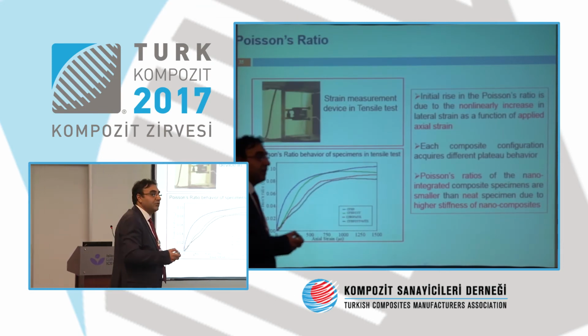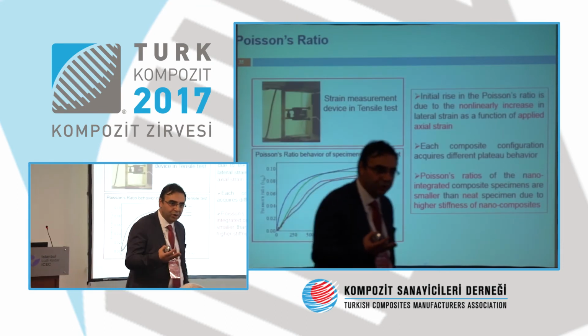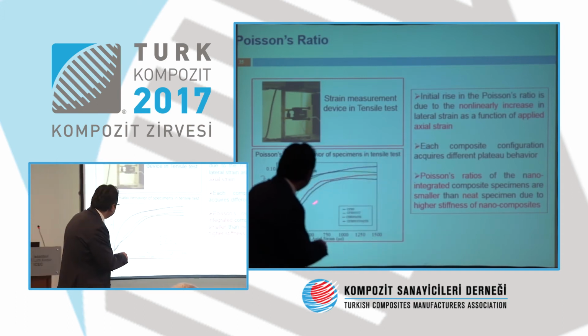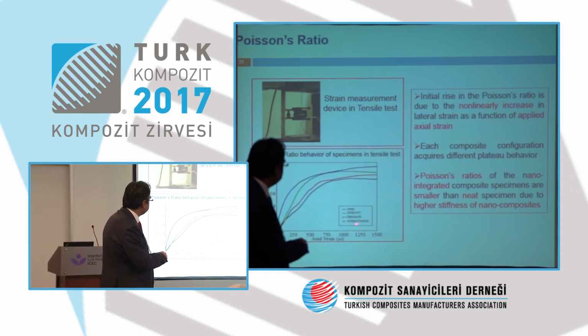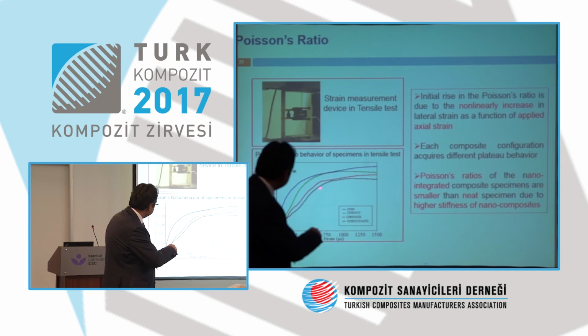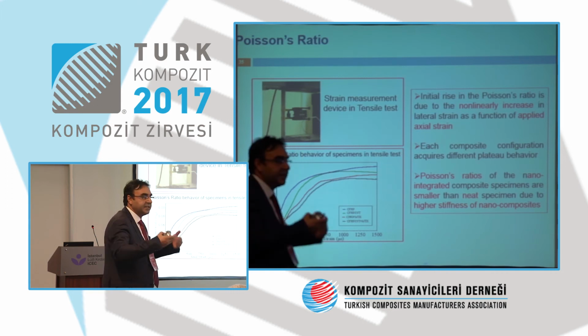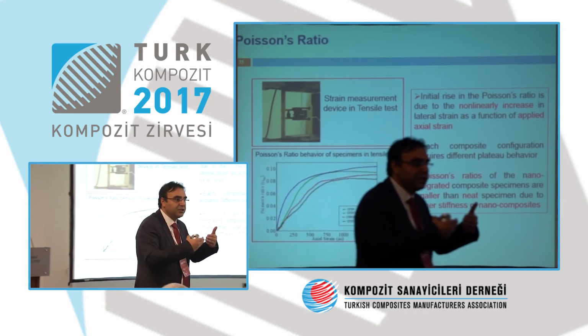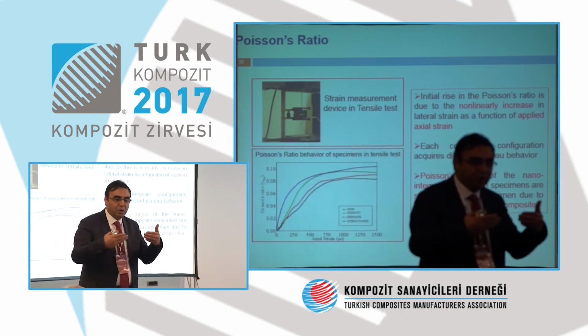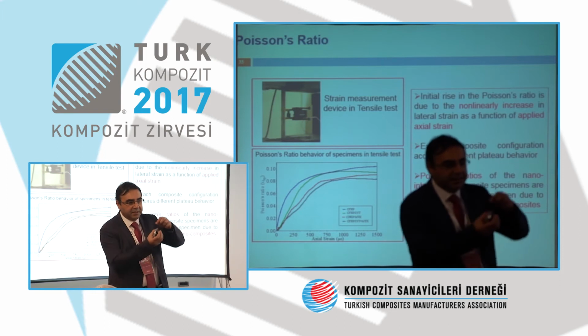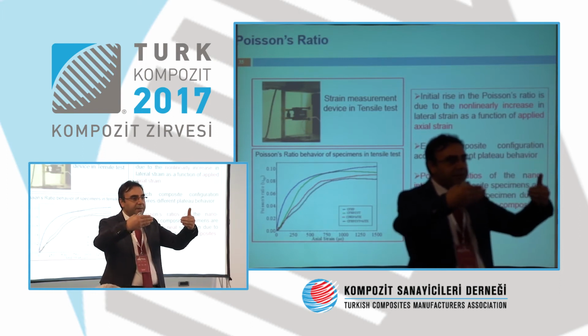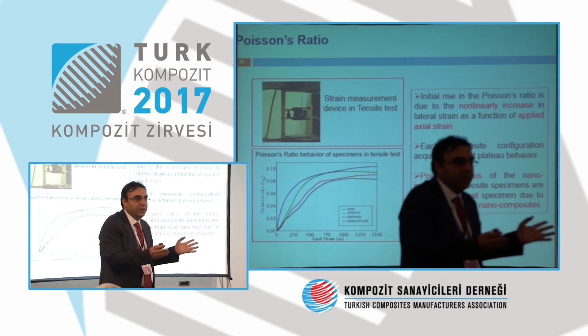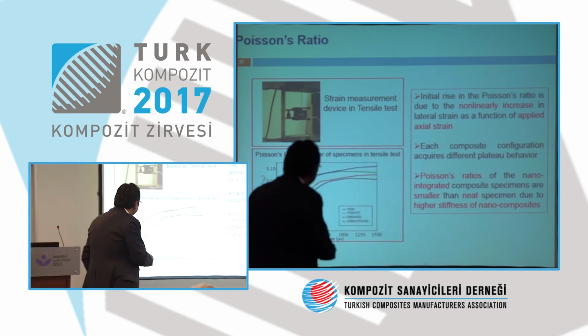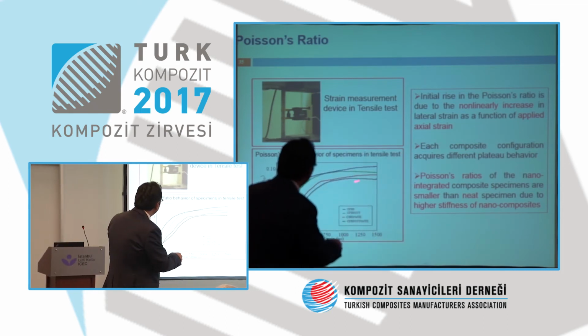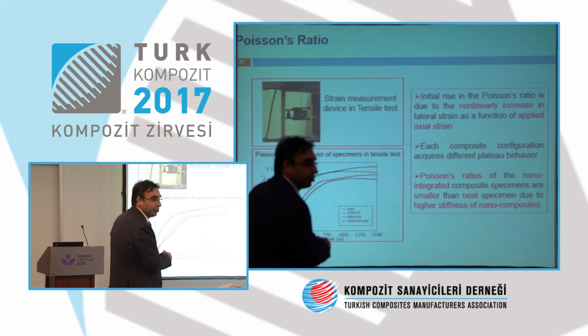Also, to characterize, we look at the Poisson ratio. If you look here, with the addition of reinforcement to the interface and matrix, this is your Poisson ratio. It basically tells you that you are stiffening your material in the transverse direction. So you have a better load-carrying capacity while you are pulling and your material is being deformed. If you did not reinforce it, then you would not be able to observe these attributes.